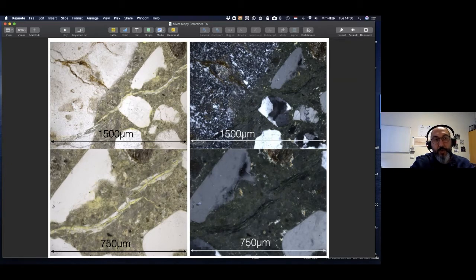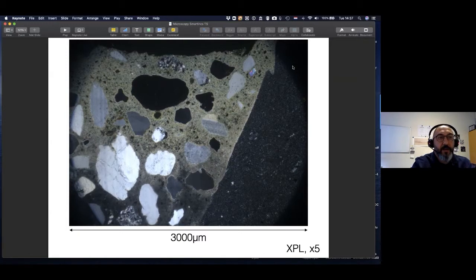that this could be responsible for alkali silica reaction, while the neighboring sand grain is not microcrystalline. You see, probably these kinds of aggregates are not susceptible to alkali silica reaction damage. Just some examples. And here there's another one which is showing a really large field of view.